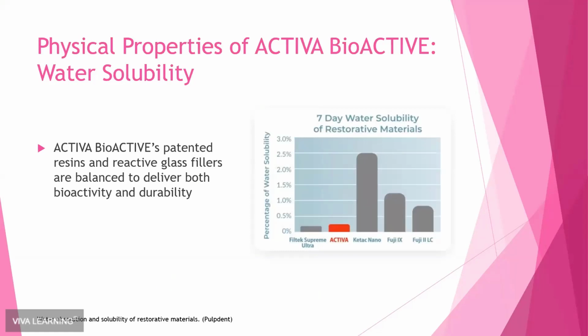And then water solubility, same thing. We're looking more along the lines of the Activa being comparable to a traditional composite, so the Filtek Supreme Ultra in this case, and showing lower water solubility than the other glass ionomers that it's compared against. This helps it to deliver both the bioactive properties that we're looking for, but to still be durable when used in a patient's mouth.